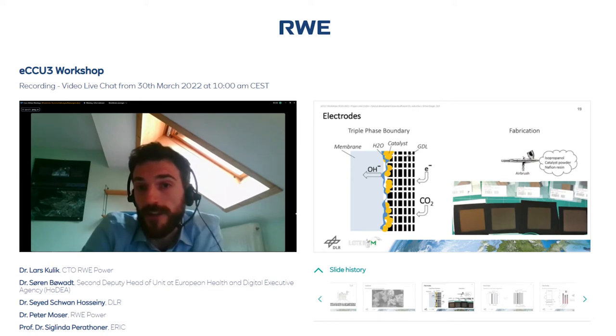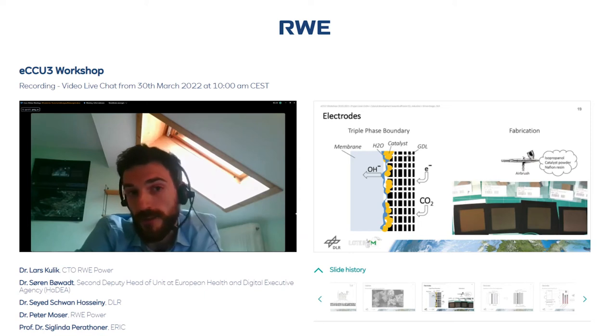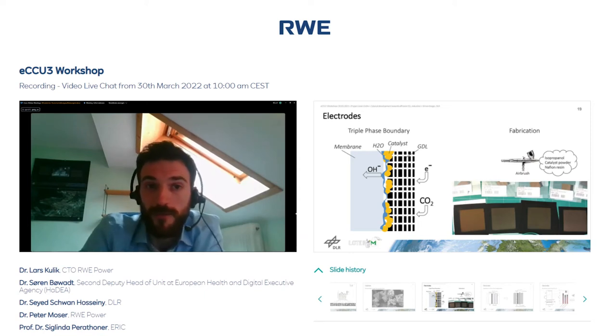And we fabricate this on the right side by airbrushing our catalytic material within some Nafion resin and also isopropanol to dilute on a commercially available gas diffusion layer that already has some advantageous properties for us, like hydrophobicity, for instance, to generate this triple phase boundary.